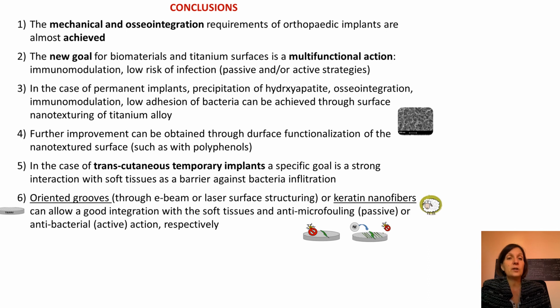And it is obtained through nanotexturing of titanium alloy through a chemical treatment in hydrofluoric acid and hydrogen peroxide. We can have a further improvement if we functionalize this surface with some biomolecules such as polyphenols. And in the case of transcutaneous temporary implants, we developed different surfaces made with oriented grooves on the surface through E-beam or laser structuring, or with a coating of keratin nanofibers. In both cases, we can obtain a good interaction with soft tissues, with fibroblasts, and an anti-microfouling passive or an antibacterial, so an active action. This last one in the case of doping with silver ions.